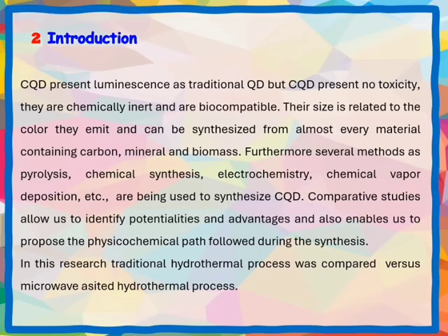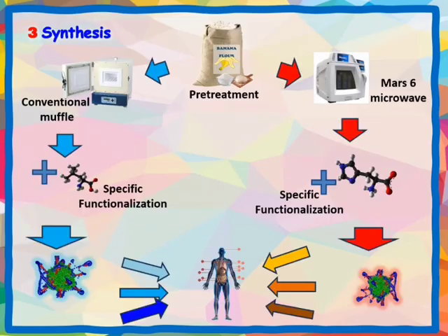Synthesis. This image schematizes the objective of the research. We start with banana peel flour and its conditioning for the synthesis. Then, the synthesis of the carbon quantum dots is performed, which in our case is doped with nitrogen. On the left, the hydrothermal method, HT, on the right, the microwave-assisted hydrothermal method, MWHT.